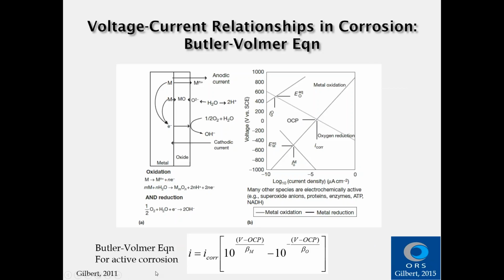by this Butler-Volmer equation. Now, this representation of the relationship between the anodic and cathodic currents is only for the case where there is no oxide film. And it's important to note that these currents rise by factors of 10, they're exponential essentially, with the voltage. So voltage shifts away from open circuit can raise the net current by orders of magnitude as it moves either positively or negatively in an electrochemical reaction. So this link between chemical reactions, releasing ions, as well as currents that flow is an important one to understand